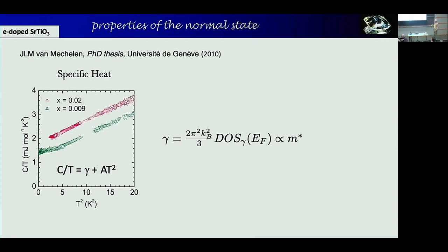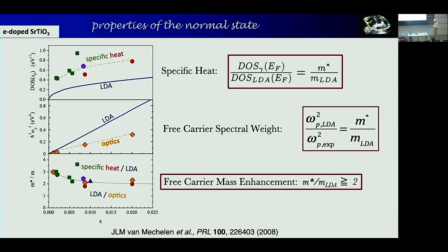So what we actually did is say, okay, we take the density of states as it is measured with this technique. We take the density of states as we actually did calculate from the LDA calculation, and that ratio tells us what the mass enhancement is. And we can do exactly the same thing also, as already explained, for the plasma frequency or for the free carrier spectral weight.